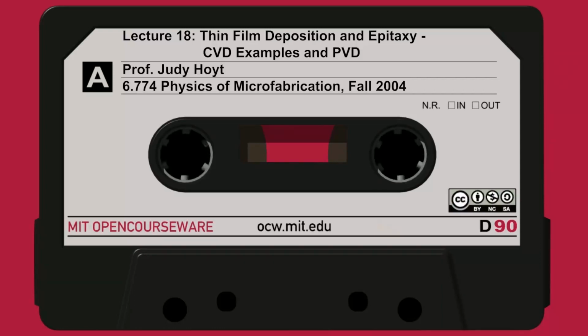So these differences between PECVD and LPCVD can affect properties like the film adhesion, the presence of pinholes. Plasma-enhanced films tend to have a little more tendency to have pinholes because, again, as was mentioned, they're going down really fast. Surface roughness can be different. A very important thing is the dielectric constant, again, because the presence of different impurities will be quite different for a PECVD. So the optical property, the index of refraction, can be dramatically different because of stoichiometric differences or because of hydrogen.